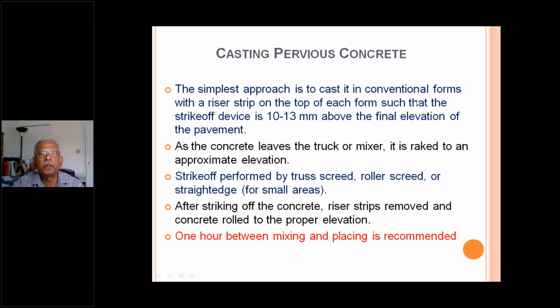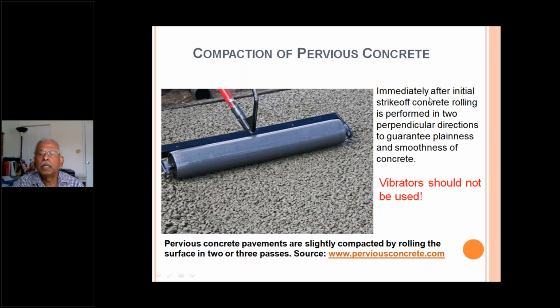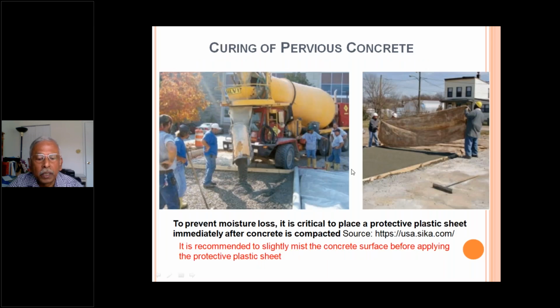This shows the casting of pervious concrete. I will skip this. The compaction is immediately after initial strike of concrete, rolling in two perpendicular directions with a light roller, and it's very important that vibrators should not be used. And this shows the curing of pervious concrete pavement. To prevent moisture loss, it is critical to place a protective plastic sheet immediately after the concrete is compacted, and it is also recommended to slightly mist the concrete surface before applying the protective plastic sheet.